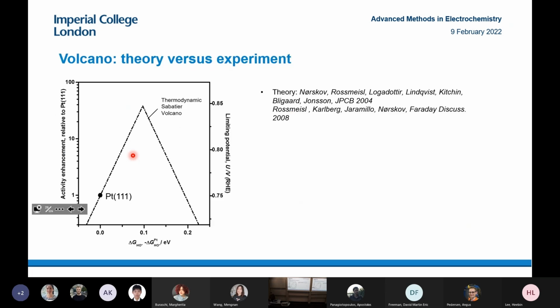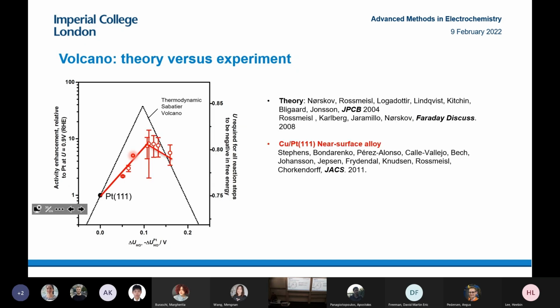Now, we've measured oxygen reduction activity, and we've also been able to tailor the binding energy and measure the binding energy, so we can actually make an experimental volcano. And this is what we found. We found it matches really, really well with the theory. We don't see quite the enhancement we expect, but we also expect that from the theory. The main thing that we get from the theory is that we get a good trend. And so we both prove the theory and we show we can actually get a high increase in activity using this near surface alloy.